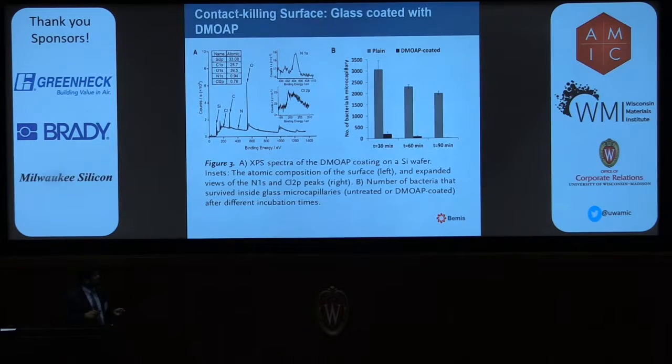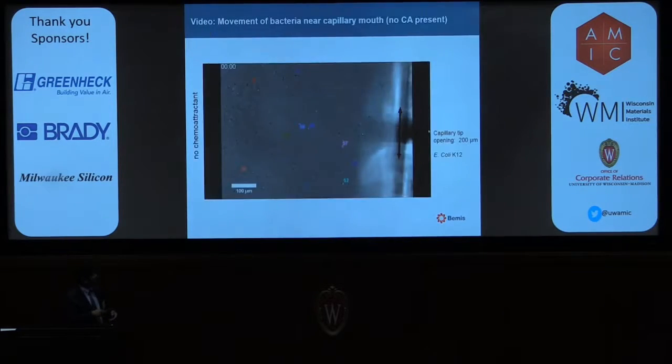And to evaluate the efficacy, we put these microcapillaries in bacterial suspensions, and what this graph on the right shows is that the contact killing antimicrobial coated on the surfaces was highly effective at killing the bacteria put inside it relative to controls, and over a period of 90 minutes it would be able to kill 99.99% of the bacteria inside.